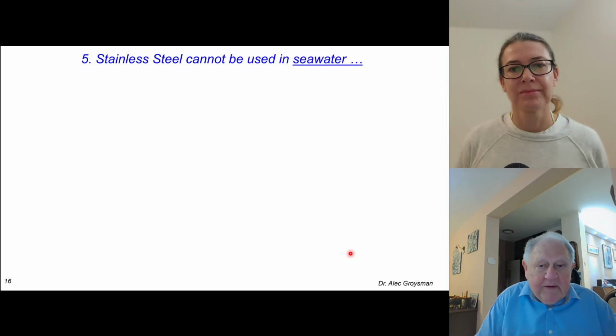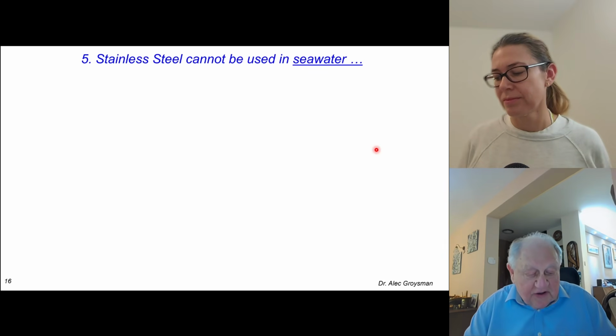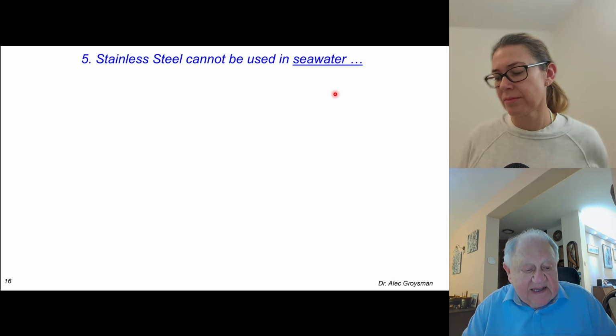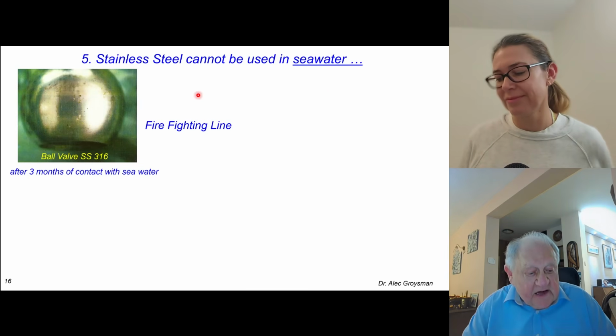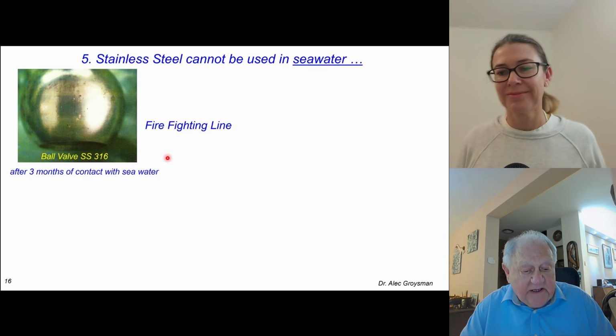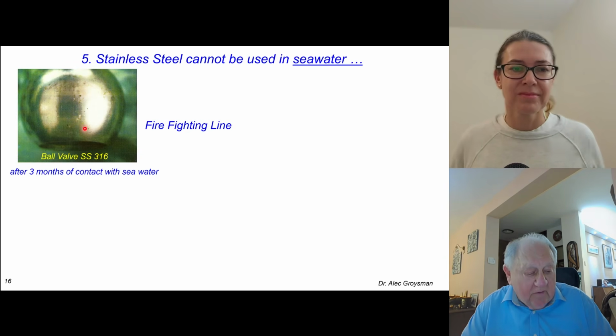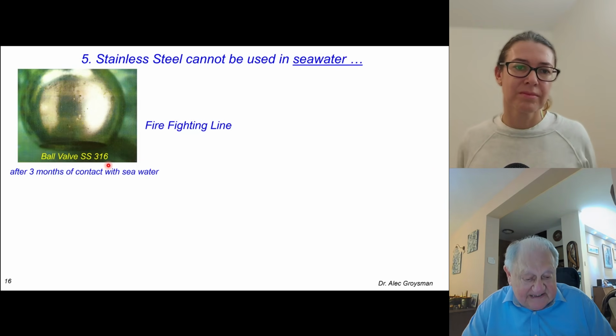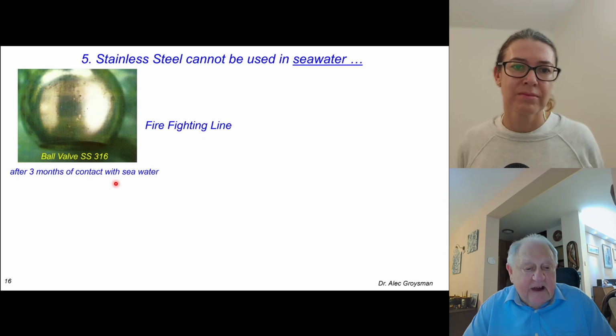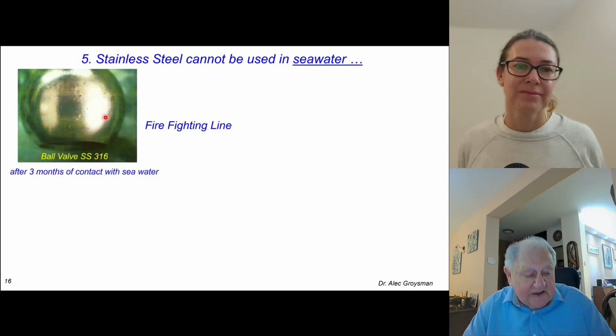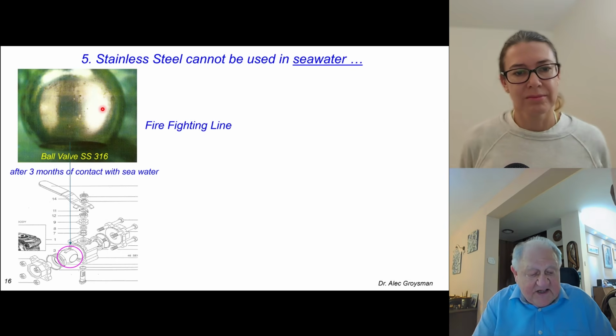Then, if you open old textbooks on corrosion 40, 50 years ago, you can read that stainless steel cannot be used in sea water. Really, at the beginning of the 1990s, one engineer at our oil refinery showed me a ball valve made from stainless steel 316 that was mounted in the firefighting line and containing Mediterranean sea water, which failed because of leakage. This ball valve served only 3 months. Pitting corrosion occurred, you see, exactly according to the textbook. We may see such tables.